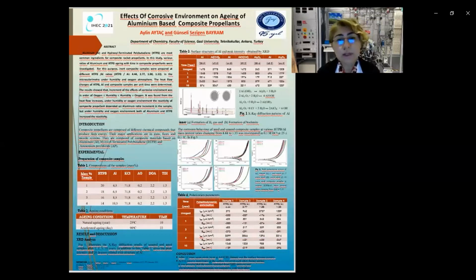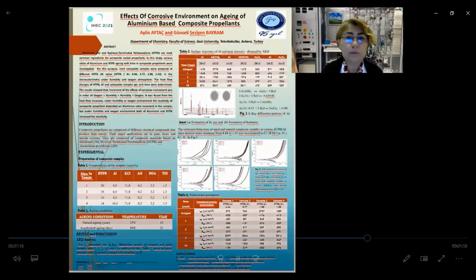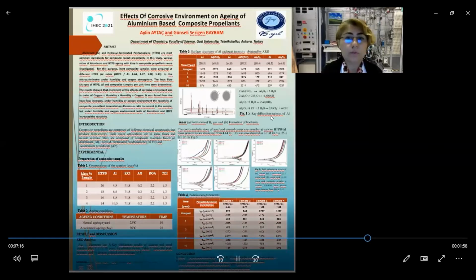On the other hand, you can see an incredible increase in the corrosion potential and the corrosion current density after 5 years of aging. This can be caused by consumption of antioxidant, plasticizer depletion, decomposition of the oxide layer, structural problems due to the thermal phase transfer, and formation of microcavities.